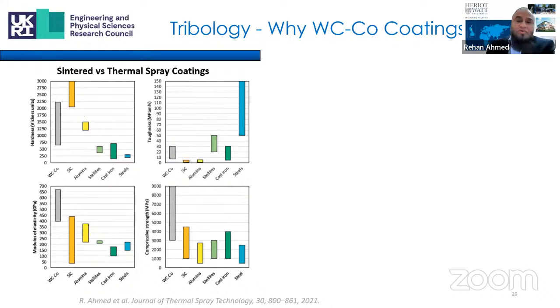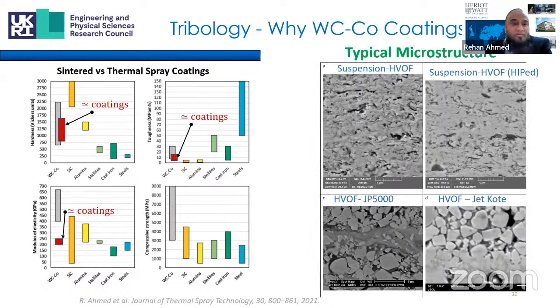tungsten carbide cobalt provides a good combination of hardness, fracture toughness, elasticity, and strength when compared to other candidate materials such as silicon carbide, alumina, and silicates. And although the magnitude of these values are lower in sprayed coatings, they still provide a good combination of properties for tribological applications in non-corrosive environment up to an operating temperature of about 500 degrees Celsius.